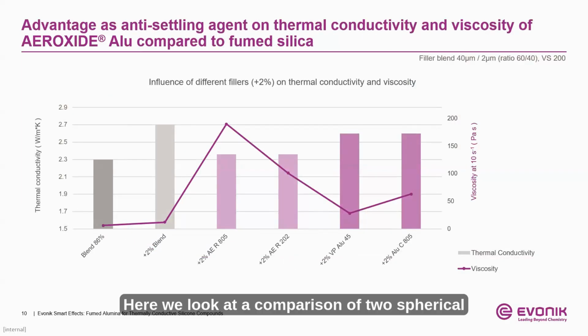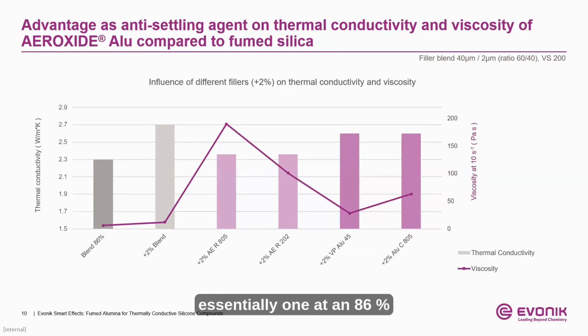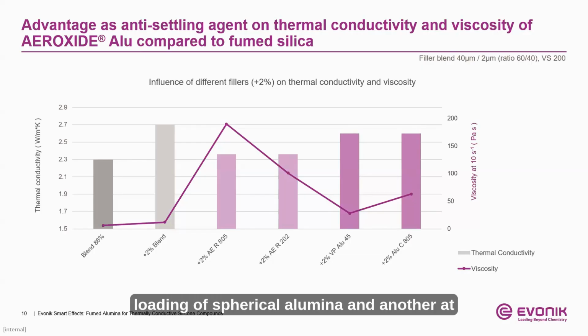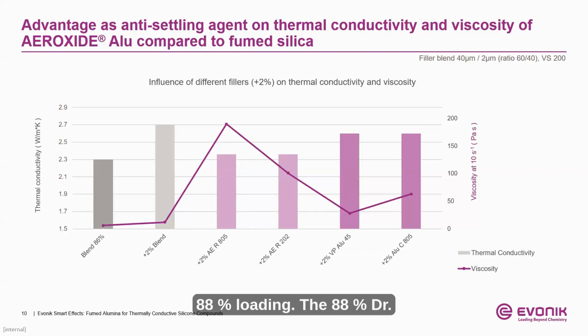Here we look at a comparison of 2 spherical alumina blends, essentially one at an 86% loading of spherical alumina and another at 88% loading. The 88% is the plus 2% blend here, second from the left. So that was the original 86% blend. Again, here we're using the 60-40 ratio of 40 micron to 2 micron, still in the 200 centipoise vinyl silicone. So the blend is the 86% of that ratio, and then plus 2% is the 88% loading of that ratio.